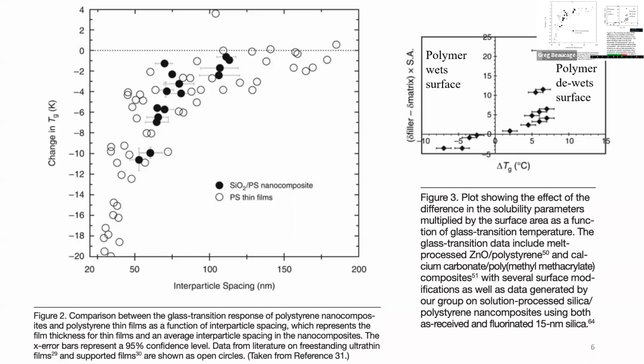Tg would go up if they're stuck, and somehow it goes down if they're not stuck. Right, so they've worked out that it's a favorable condition. So you can convert the Tg shift to the delta parameter, which is like the chi parameter. The difference between these things squared is the chi parameter. So this is the Hildebrand delta, like a number that says if things are going to be miscible. When that's 0, they're miscible. When that has a positive number, they're immiscible. So basically, this is using thermodynamics to talk about what could be kinetically mixed systems, right?